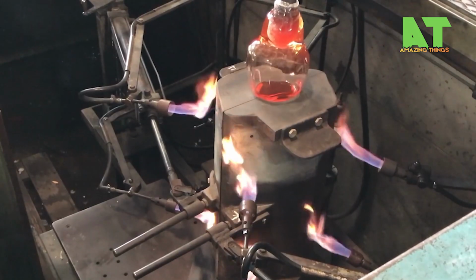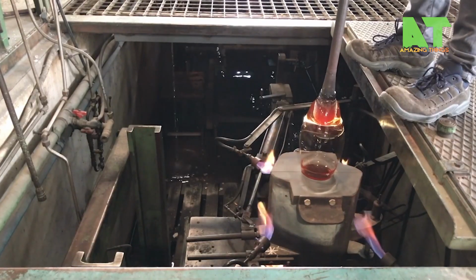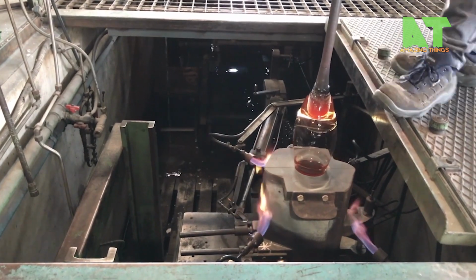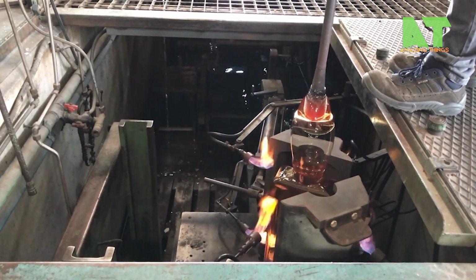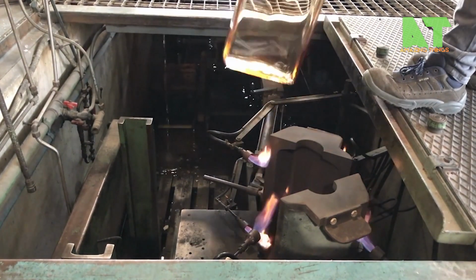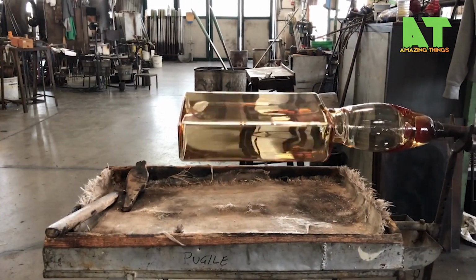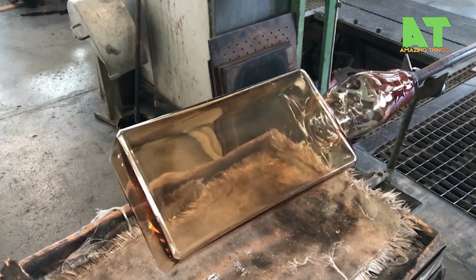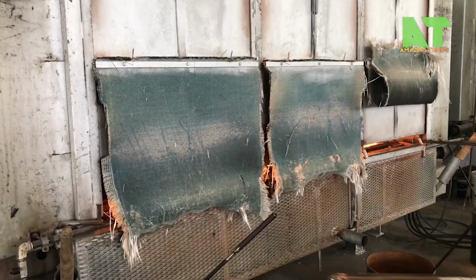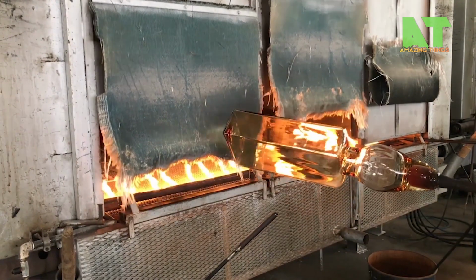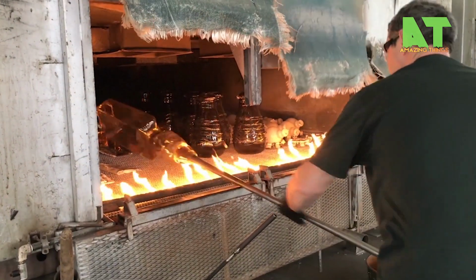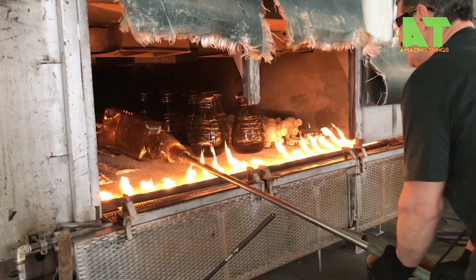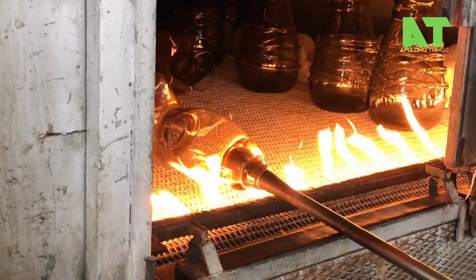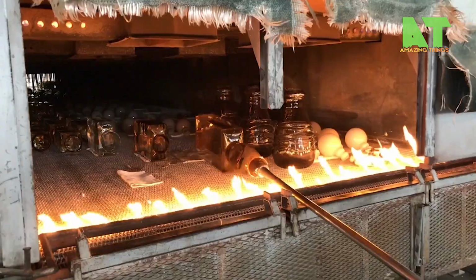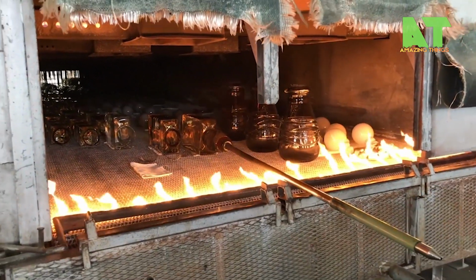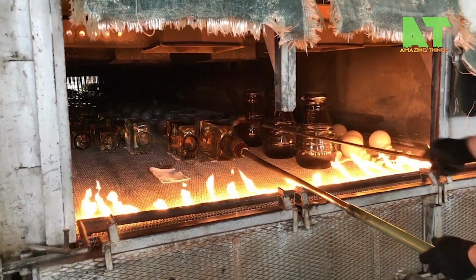The actual blowing begins with gentle, steady breaths through the pipe, creating a bubble inside the glass gather. Watch how small the initial inflation is. Blow too hard, and you'll create thin spots that'll crack during cooling. The skill lies in maintaining even wall thickness while expanding the form. Between blowing stages, the piece gets reheated in a smaller furnace called a glory hole, necessary because glass cools quickly and becomes rigid. The glass blower uses various hand tools that haven't changed much since Venetian artisans perfected them in the Renaissance. Wooden paddles to flatten, metal jacks to create openings, and shears to trim excess glass.